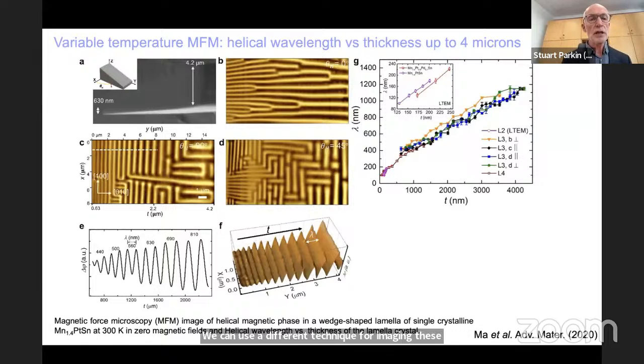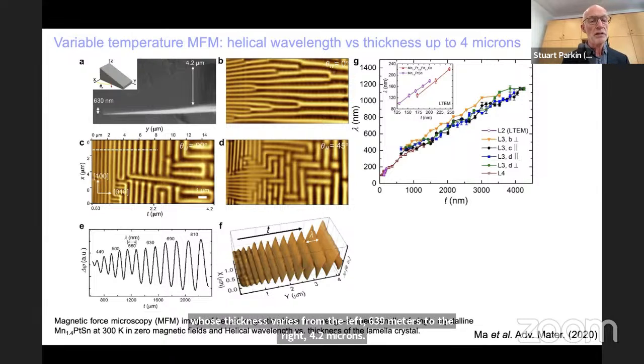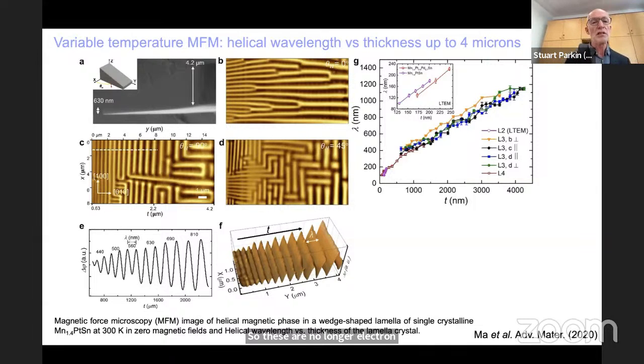This is variable temperature magnetic force microscopy, in which case we're no longer probing the in-plane components, but rather the out-of-plane components. And in this case, instead of making a lamella with a uniform thickness, we've made a lamella whose thickness varies from the left, 630 nanometers, to the right, 4.2 microns. So these are no longer electron transparent. And the reason for exploring this thickness range was to try to understand why the size of the skyrmions, and in this case, the one-dimensional helical structure, the period of that structure, evolves with thickness.